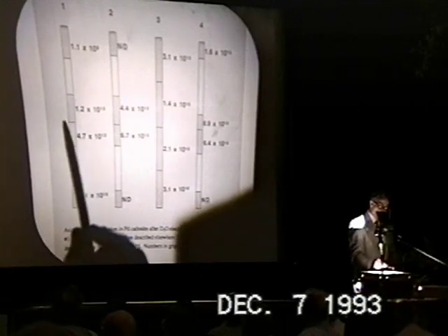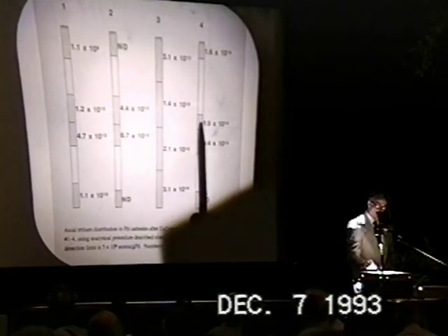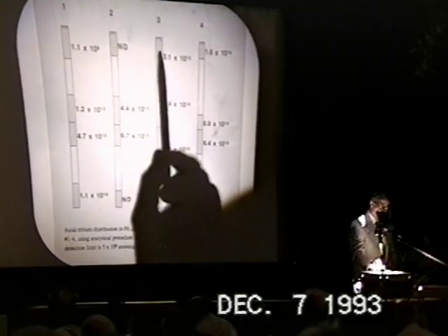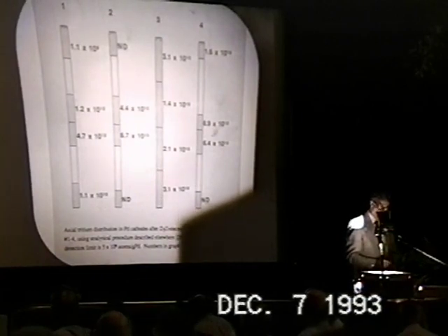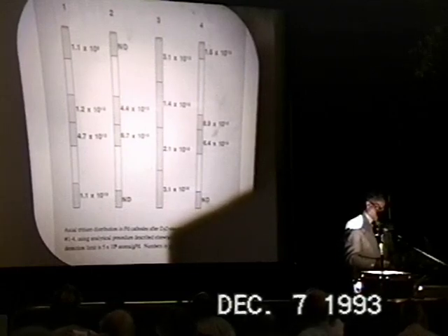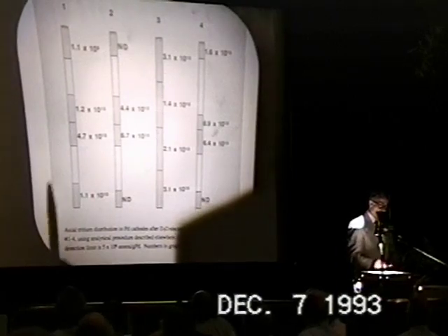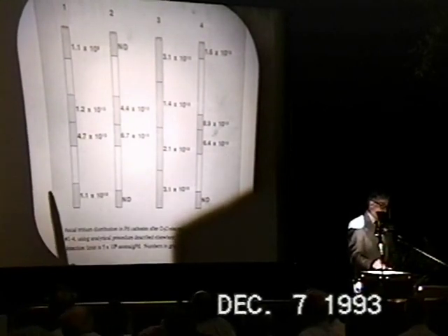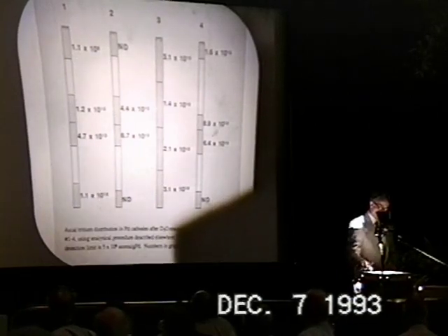What we found is that more tritium usually was obtained near the center than near the ends of the electrodes. This, in our opinion, could mean one of 2 things. Either the ends didn't charge as effectively, and hence the tritium generation here was smaller than near the center of the wires, or that tritium indeed was originally formed near the ends as much as the material, but had, of course, more of a chance to diffuse out through the ends than away from the center.